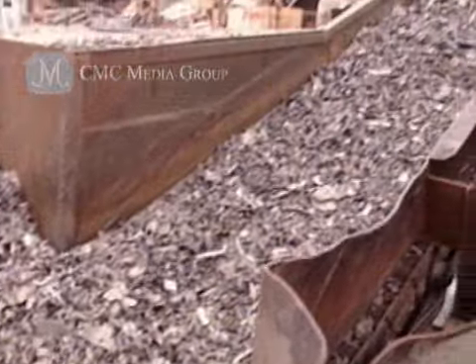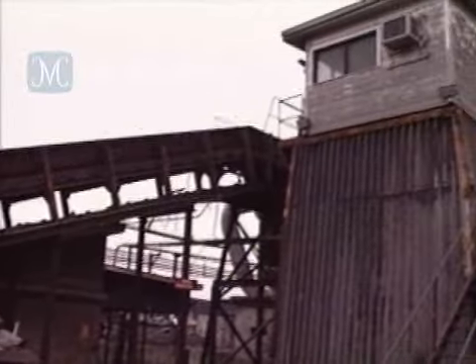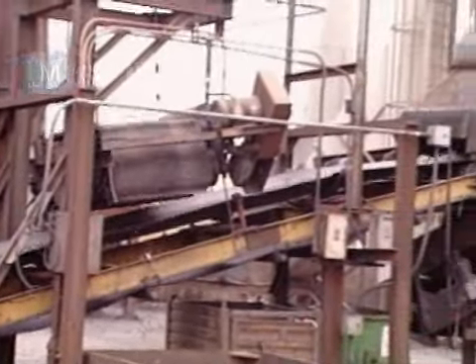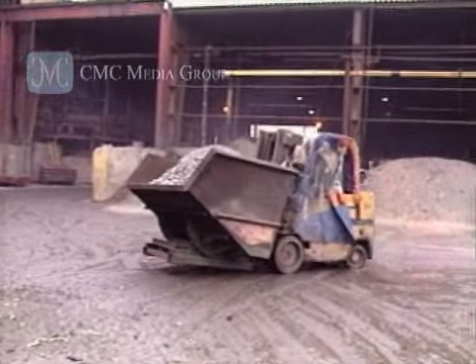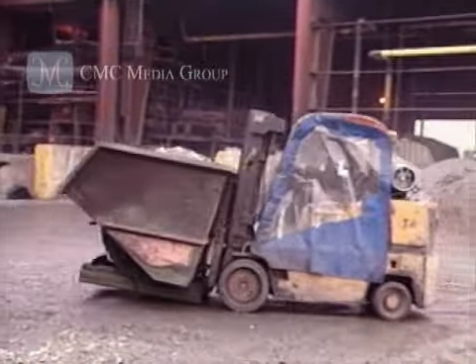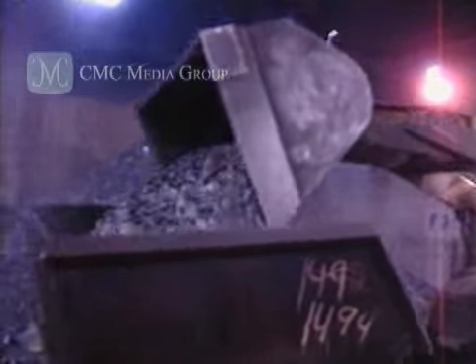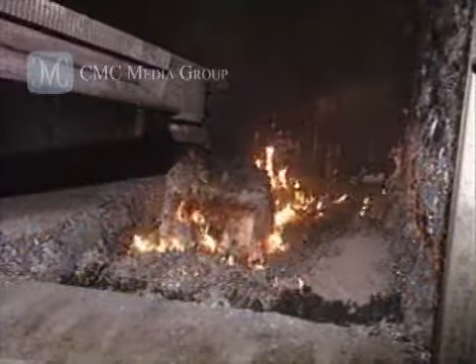Processing is an important part of our business. Its purpose is to prepare scrap for the furnace and maximize recoveries by removing burnables and free iron, paint, grease, rubber, dirt, and oxides. Drying, shredding, sweating, and rotary furnace are the most common processing techniques. Once the scrap has been processed, it is now moved into furnace-ready bins, where it is segregated by analysis and anticipated recovery rates.